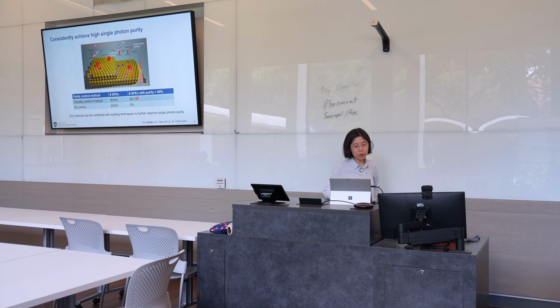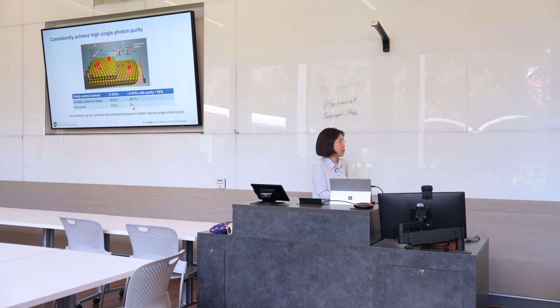In contrast, if we don't use any of the purity control methods, if you just look for single photons on your sample, among all the spots we measured, only 29% of them are single photon emitters, and none of them are of high purity, over 90%. So basically, this method is very consistent. It helps you to achieve good single photon purity.